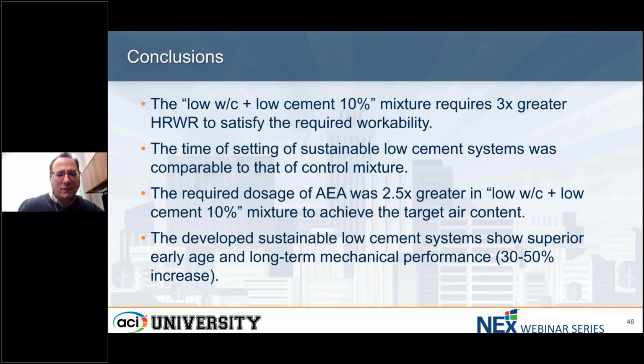So based on what we discussed so far, these are some conclusions we can derive from the data we have. The low water cement ratio, low cement system with 10% reduction in the cement requires 3 times higher high range water reducer content to satisfy the workability requirement, which is the slump value. The impact on the setting time was not much; the data was comparable. For the air entraining admixture, the required content increased by 2.5 times to achieve the target air content. The developed sustainable low cement system improved the mechanical performance by almost 30 to 50%.